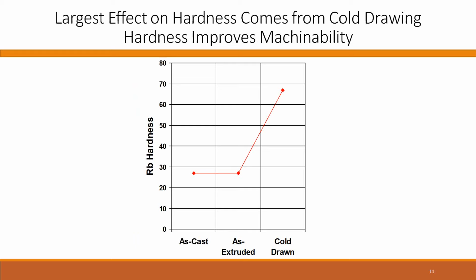The effective hardness that you need to get the best machinability can be seen here. When you've got a casting or an as-extruded but not cold-drawn product in front of you, the hardness is about the same, and they're both pretty low, and that's what makes it a gummy machining material, even though you've got lead or bismuth or sulfur or something in there. But cold drawing has a very strong impact on the hardness, so that helps the machinability, but it also works against you in terms of being able to cold work through thread rolling or bending or whatever you need to do to make your final product. So the amount of cold work is carefully controlled to achieve the best balance in the hardness in terms of the best machinability and the best thread rolling.